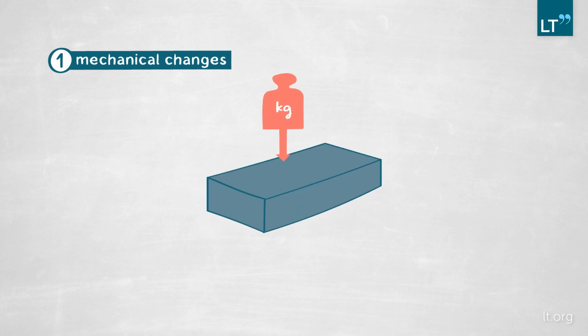But what about hydrogen? For that, we developed our own in-house, in situ hydrogen charging cell. This is basically an electrochemical cell that is placed beneath our sample, and we produce hydrogen in there by using the hydrogen evolution reaction, and the atomic hydrogen will further move towards the upper surface tested by nanoindentation. This particular method that we are developing will allow us first to track particular changes in the mechanical behavior that are related only to the presence of hydrogen. And this is because no other effects are expected on the sample surface.